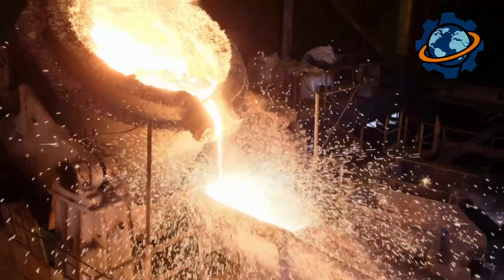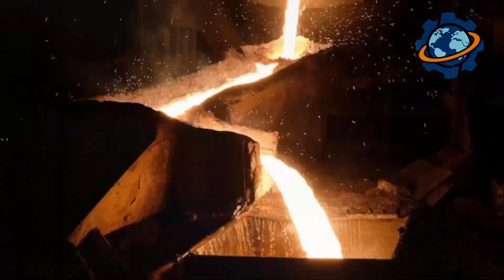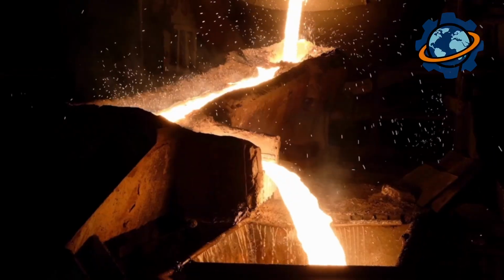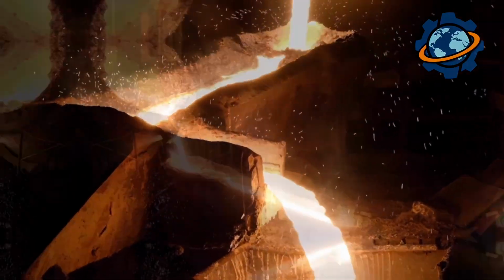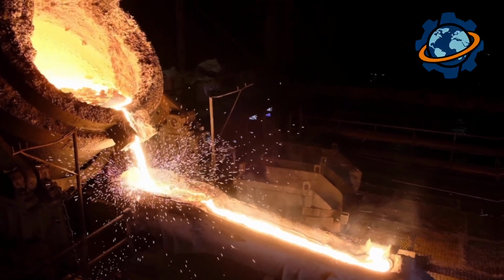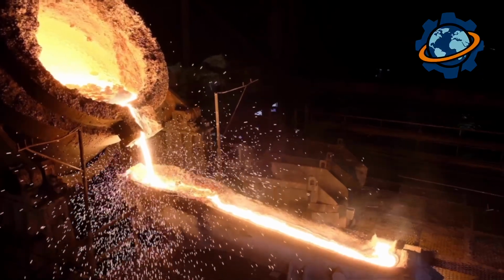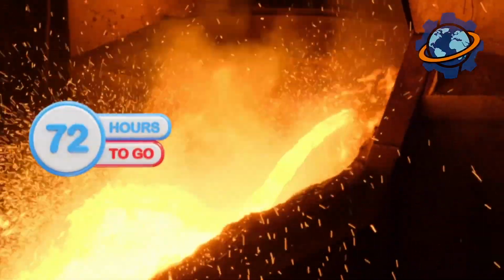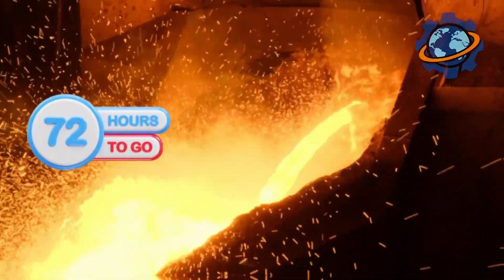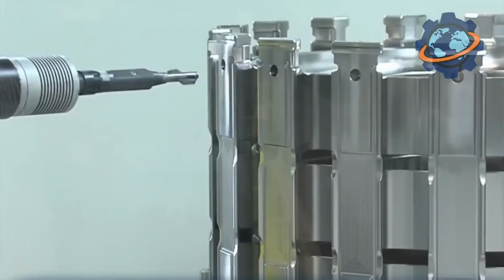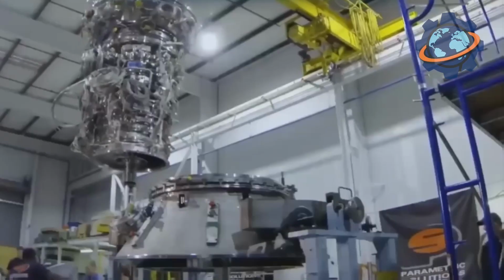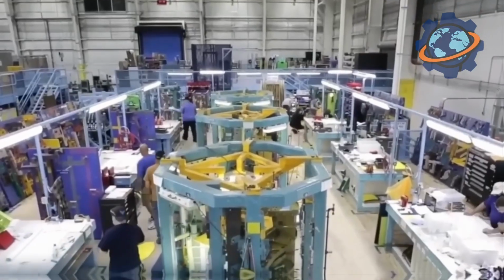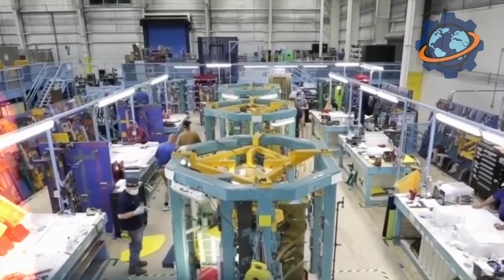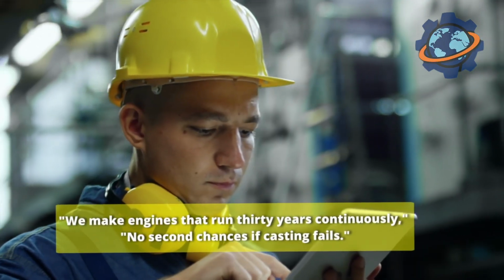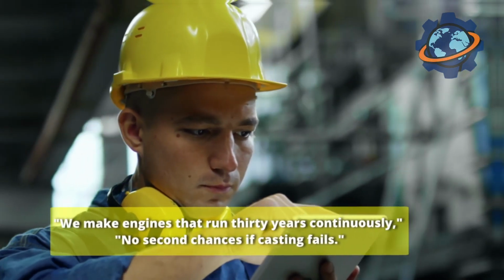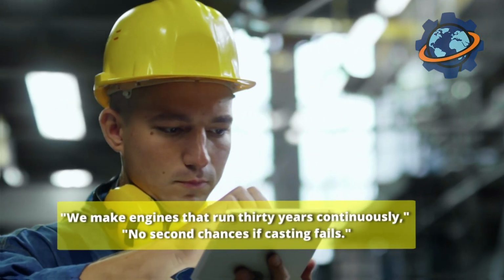Watch the cylinder casting. Molten iron pours into sand molds, creating a single cylinder liner. Hollow tubes where pistons travel. Each liner stands 12 feet tall, walls 4 inches thick. The iron must cool for 72 hours. Rush it, and thermal stresses create microscopic cracks that propagate under operation, causing catastrophic failure. "We make engines that run 30 years continuously," explains the Chief Engineer. "No second chances if casting fails."